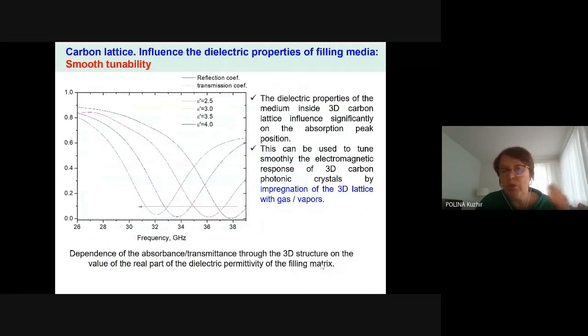You could also fill your open porosity structure with different dielectric media, and this will allow you to substantially switch the position of the absorption peak. For instance, in this particular case, when you fill the structure with dielectric media with permittivity from 2.5 to 4, you will change the position of the absorption peak from 40 gigahertz to almost 30 gigahertz.